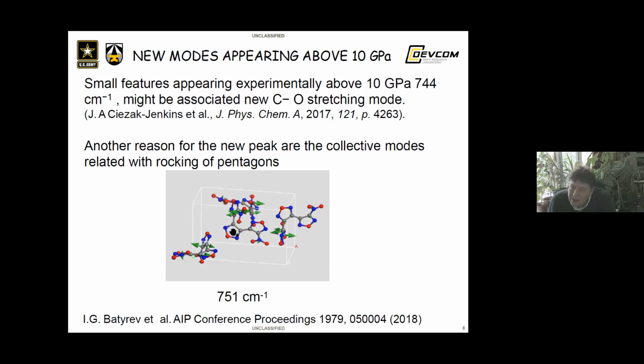We don't see these drastic changes in the Raman spectra. So there is another reason for the new Raman peak around 750 inverse centimeters, and it might be related to collective modes. It is shown here. Enhanced rocking of pentagons above 10 GPa results in the new mode. So there are two explanations of this emerging new peak above 10 GPa.